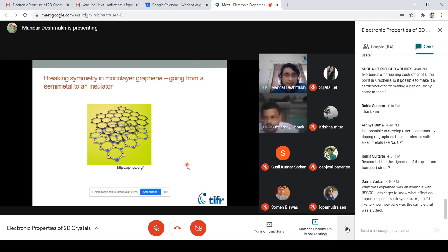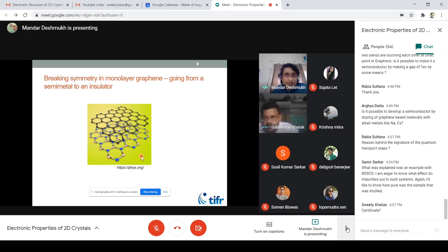because boron nitride has a band gap of about 6 electron volts, so it's really not a good material for semiconducting devices. But there are other materials which are not using carbon, called molybdenum disulfide, or which are called dichalcogenides, which have formula MS2 or MSe2, and they, in some sense, are exactly what you desired in your question. Their crystal structure is 3 atomic layers, but effectively it's like a honeycomb lattice, with this being a different chemical species. So they don't have inversion symmetry, and they have a band gap of close to 1 electron volt. So it exists.